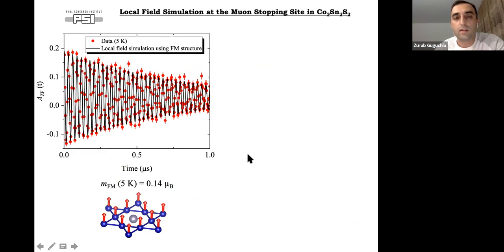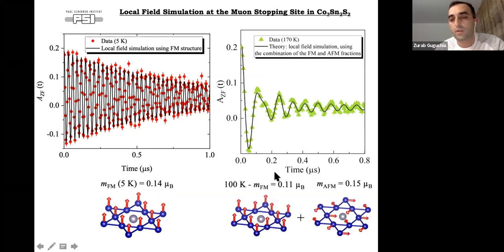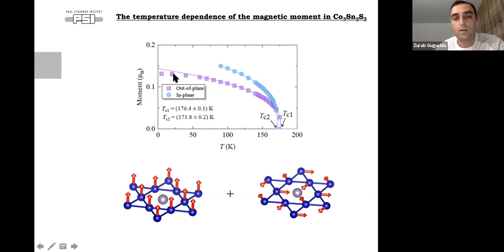After knowing the muon stopping site, we did the local field simulation considering these two different structures. What we find is that the base temperature spectra can be well described by the out-of-plane ferromagnetic state with a moment size of 0.14 μB, while the high-temperature state can be modeled by combining the ferromagnetic state and the antiferromagnetic state with slightly different moment sizes. It lines up with the data very well. Based on the simulation modeling, we can nicely follow the temperature evolution of this small moment size, 0.14 and 0.15 μB. And we find two different transition temperatures for these two different structures. So this muon stopping site calculation and local field analysis show that the high-temperature structure is the in-plane antiferromagnetic state, and we have a large temperature range where these two structures coexist or compete.